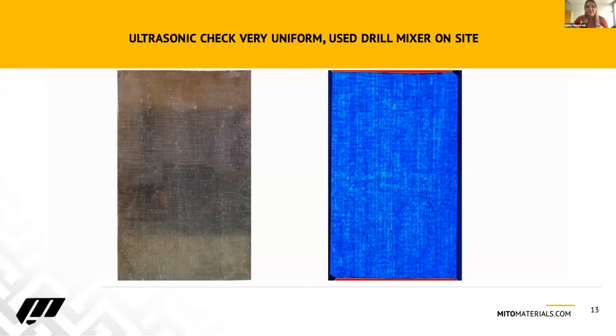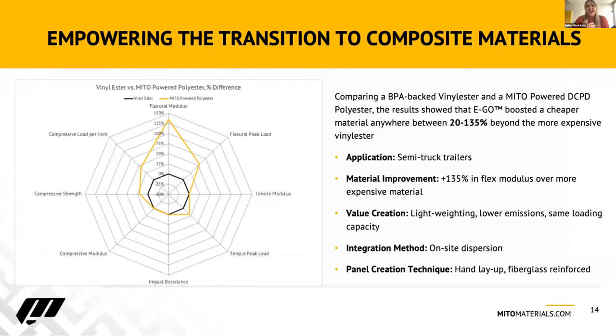And here you see an ultrasonic check for a very uniform dispersion of our additive into their polyester system with a simple drill mix attached on site. This dispersion happened in-house at the facility using a simple shear mix. So the uniform dispersion on these ultrasonic panels and the test results that we gained thereafter showed an increase from MITO plus polyester, 135% increase in flex modulus over the vinyl ester opportunity that they were evaluating.